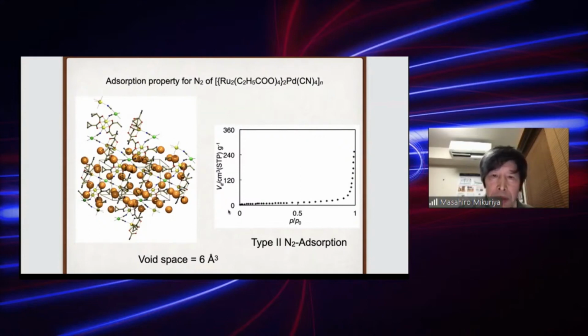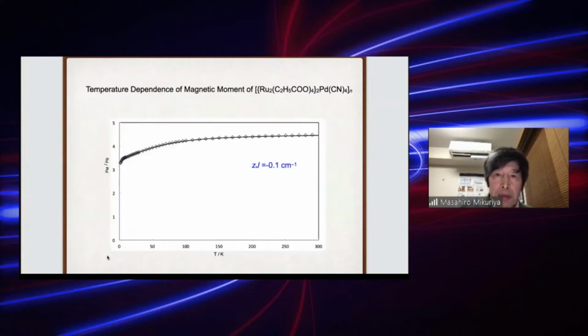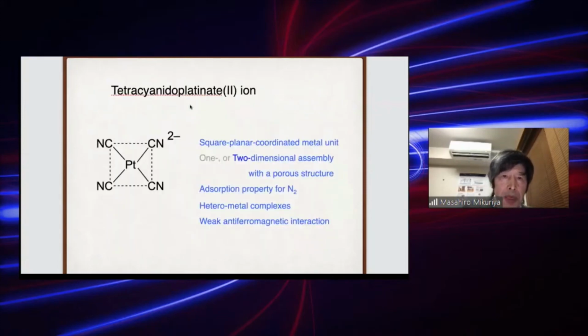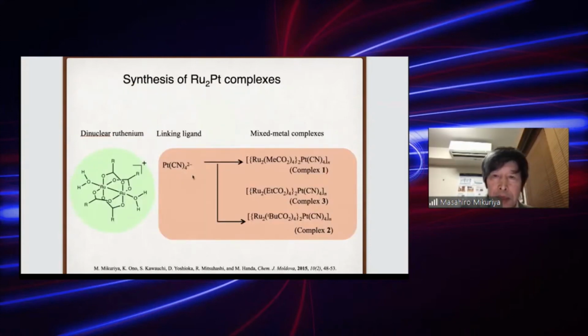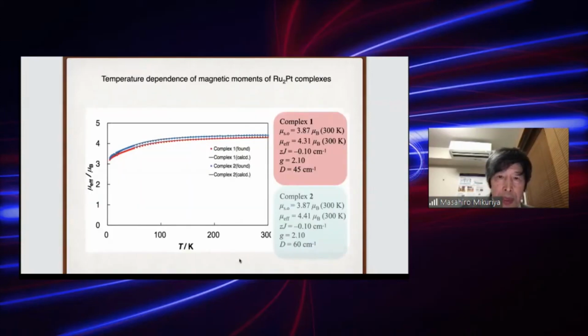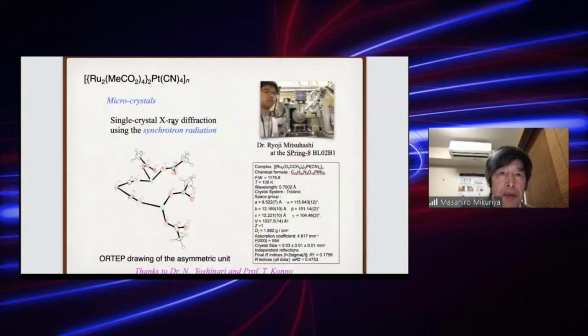But we got the type 2 adsorption, because of the very small void space here. Magnetic interaction is very weak antiferromagnetic behavior we observed. So next we used platinate linkers. By using tetracyanoplatinate, we obtained some assembled compound. Magnetic behavior, very weak antiferromagnetic types we obtained. And for this one, very small crystal we obtained.